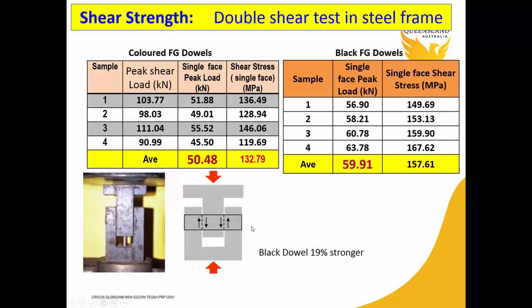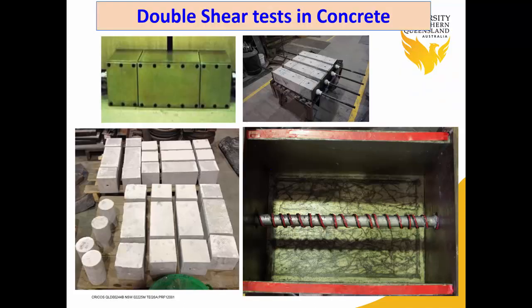The result of the test is shown in these two tables. The left one shows the data for colored fiberglass dowels, and the right one shows the data for black fiberglass dowels. As shown here, black fiberglass dowels are stronger in the order of 1 ton compared to colored fiberglass dowels, or 20% stronger. Black fiberglass dowels are almost 20% stronger than colored fiberglass dowels.